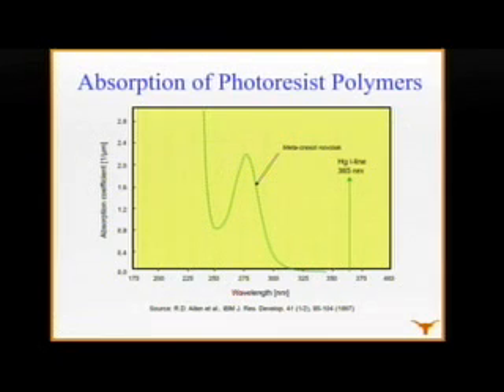Unfortunately, as we progress to smaller and smaller structures, we're doing the exposure at the so-called i-line of the high pressure mercury lamp, 365 nanometers, and everything was working fine. This is the absorbance spectrum of the Novolac resin. It's transparent up here, but it absorbs light at shorter wavelengths. In order to make higher resolution, I need to move over here, and you can immediately see there's a serious problem. That resin, which is transparent over here, looks like aluminum foil at that shorter wavelength. It's absolutely opaque. So no light can reach the lower reaches of the film to do the chemistry necessary for patterning. That chemistry is not going to work.